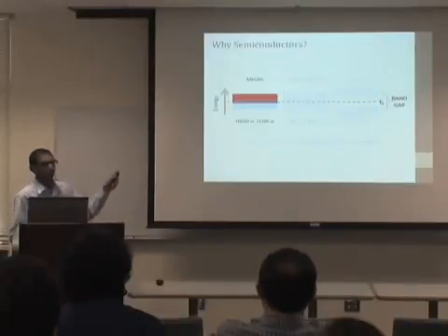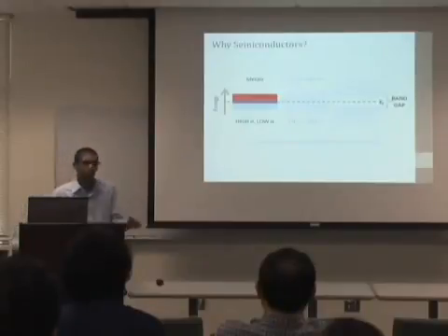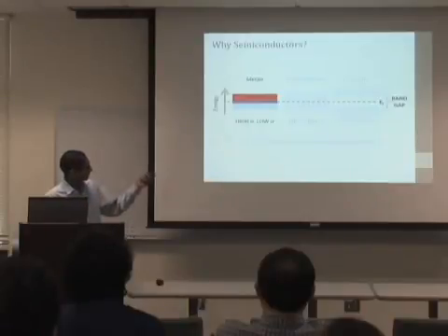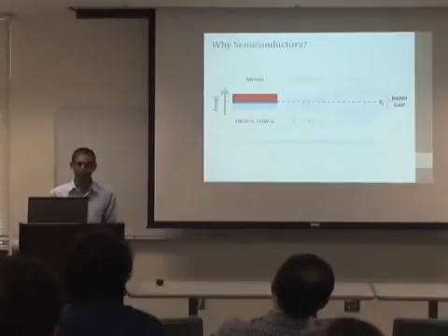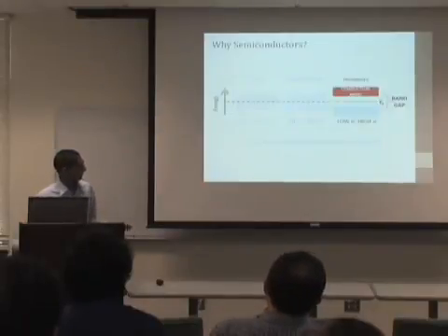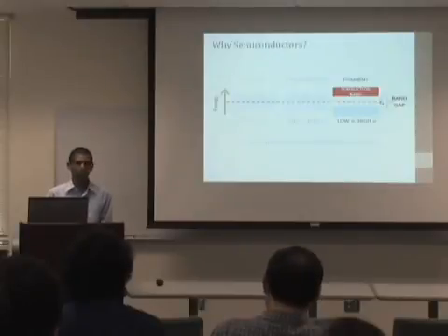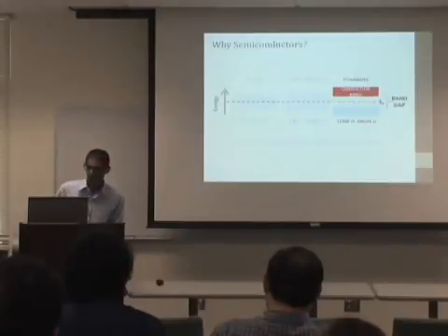In metals, these two bands overlap. So that's why metals are always conductive. And if we go back to that trend that we noticed, these basically have a really high carrier concentration, so they're going to have a high conductivity and a low Seebeck coefficient. On the other hand, insulators have a very wide band gap, which means they have a low carrier concentration and a high Seebeck coefficient. These aren't ideal when we're trying to maximize that power factor.